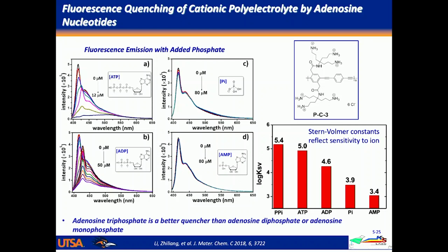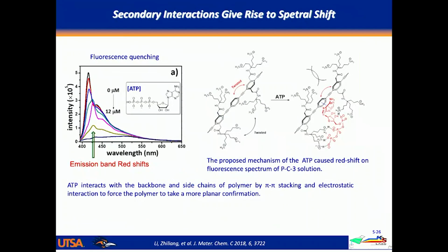But what's a little bit more subtle here is that if you look really carefully at these spectra, you'll notice that this isn't just simply quenching taking place. There's actually shifting going on in the spectra as you add more of the pyrophosphate, or in this case, ATP to the system. So we believe that there's some specific molecular interactions taking place that give rise to changes in the conformation of the backbone that are reflected in the emission spectra as you add more and more of the quencher. And what I'm talking about here in particular is you'll see this peak that starts out at about 420 nanometers. It shifts to about 430 or so as you add more of this ATP, and then finally it quenches almost all of it and becomes this broad-shaped spectrum.